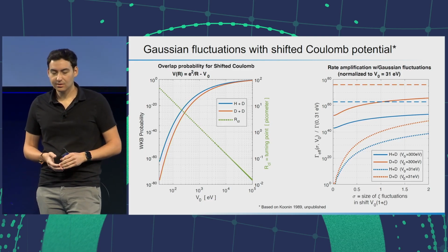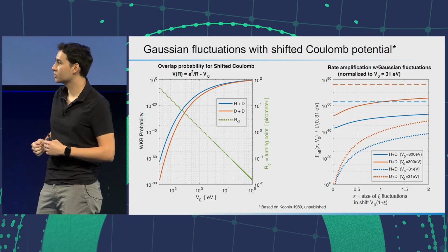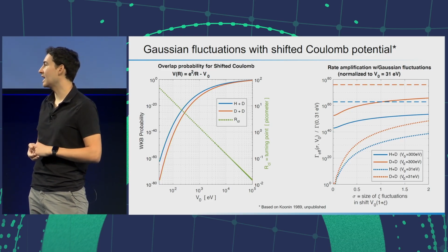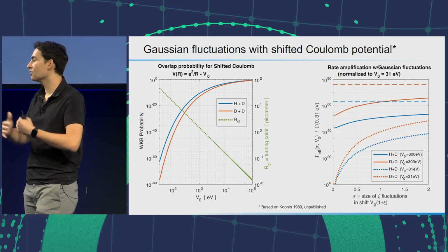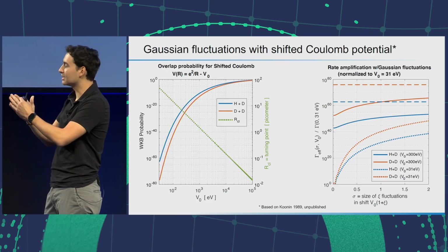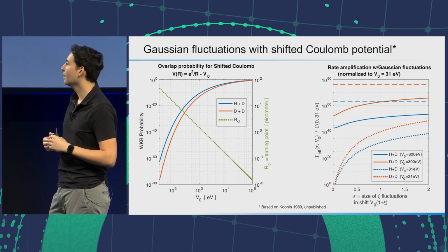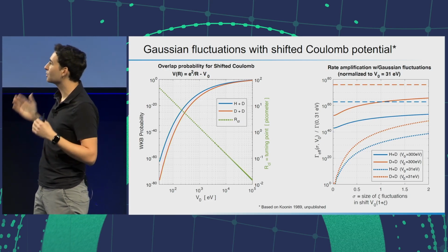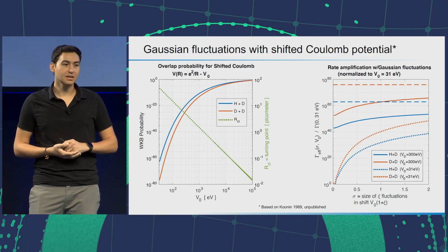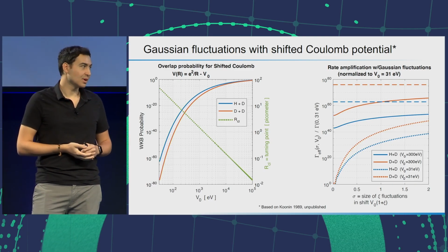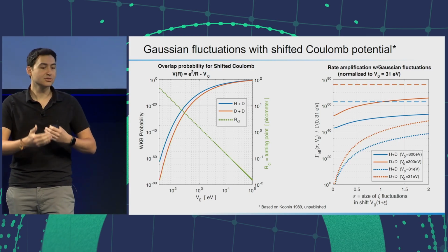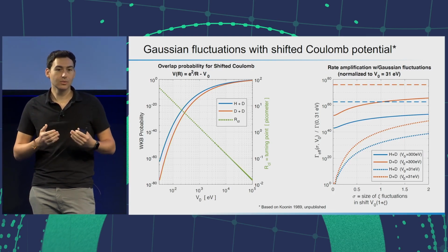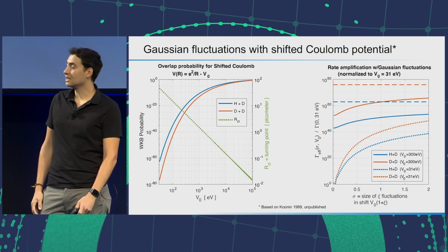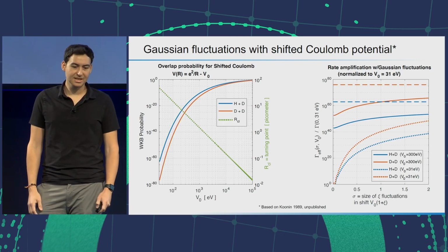But the key takeaway here is that when we start turning on fluctuations by tuning across this horizontal axis, that's increasing the strength and range of these fluctuations. If you like, it's a Gaussian, so you're broadening that Gaussian. We see a large enhancement, 10, 20, 30, 40 orders of magnitude in the amplified fusion rate due to fluctuations. And so the takeaway here is that when we introduce fluctuations into our system, we could see large enhancements in the fusion rate. So that was the conclusion from this calculation.